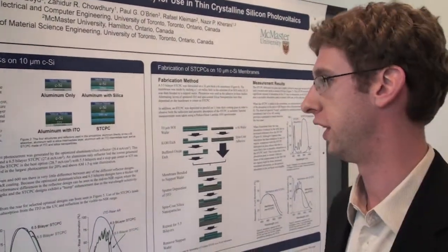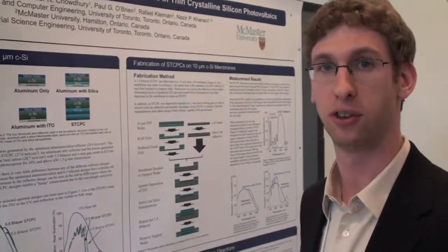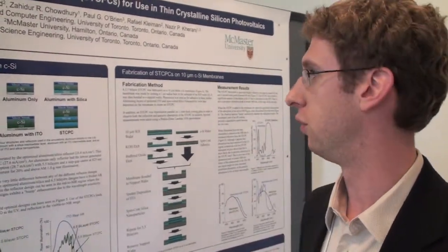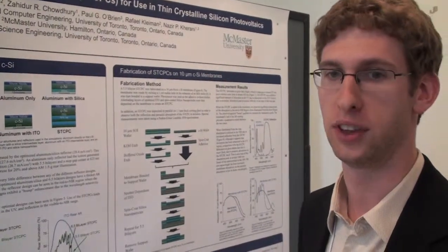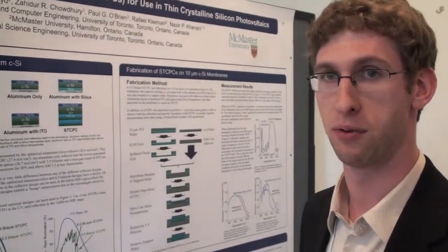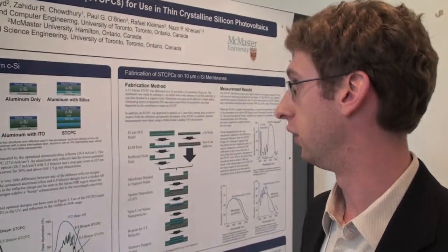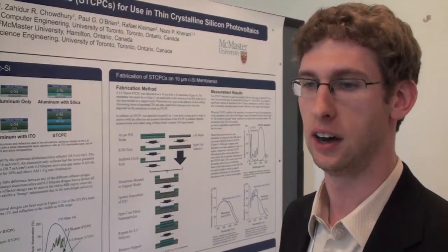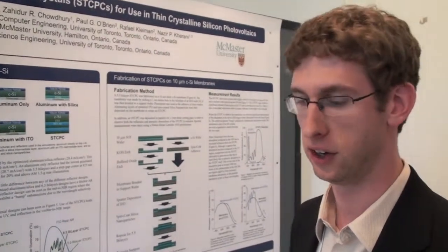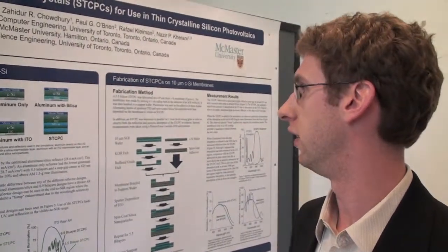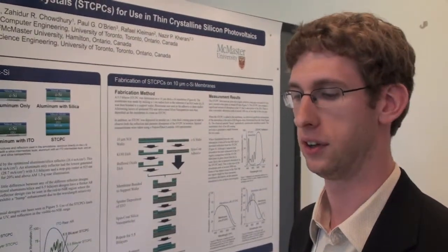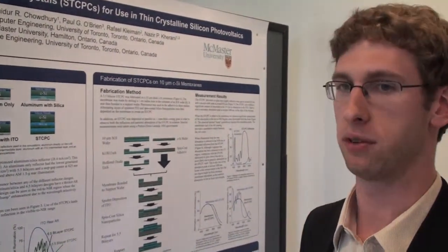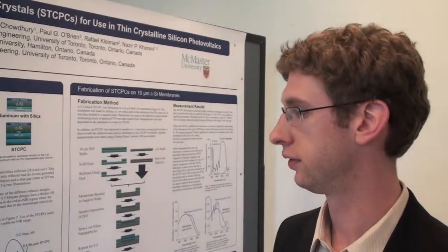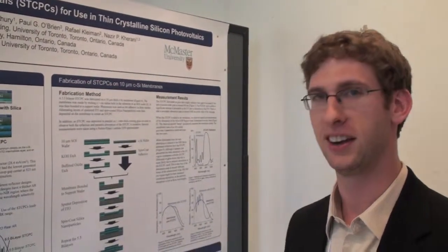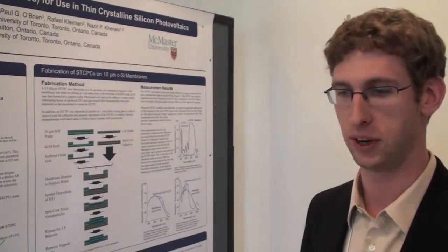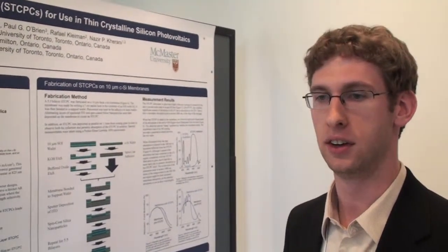The results in terms of simulation were that, yes, when we take into account just illumination from the front, your aluminum reflectors, particularly the one with the silica intermediate layer, have slightly better performance. But when we include rear illumination, say about 10% of the solar spectrum from the rear in addition to 100% from the front, then the photonic crystal on the back is preferable and has slightly improved performance. In line with that, we thought, okay, next step, let's make one and see if we can fabricate it on a very thin silicon membrane.